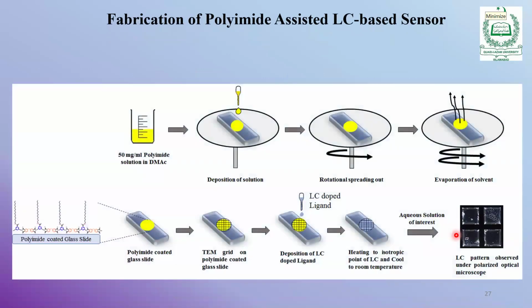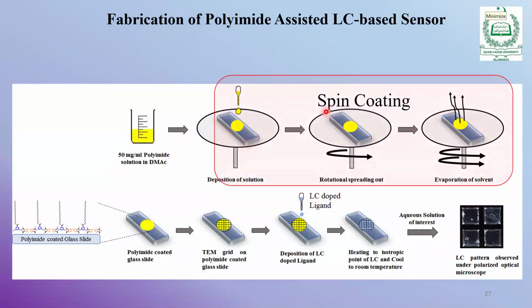Now about the fabrication of polymer-based liquid crystal sensors. We used a solution of polyimide in DMAc, and we spin coated the solution on the glass plate. So this is the rotation spreading out under vacuum of the polymer sample. The solvent is evaporated, it is dried, and it is coated. So you see here the polyimide is coated on the glass plate. Glass has OH, and in the structure of the polymer there are various electron donor and electron acceptor species. There are carbonyls, nitrogens, imide linkages, NHs, so they can interact with the OH of the glass to form a very good coating on the glass slide.